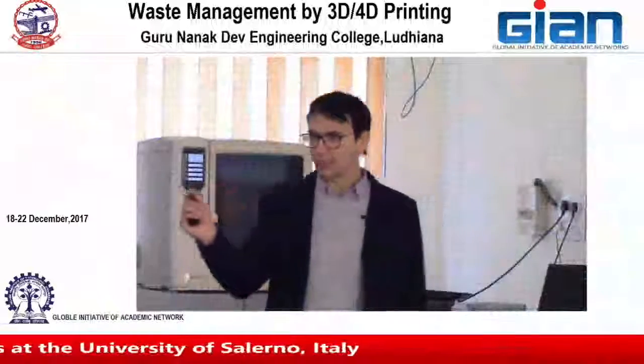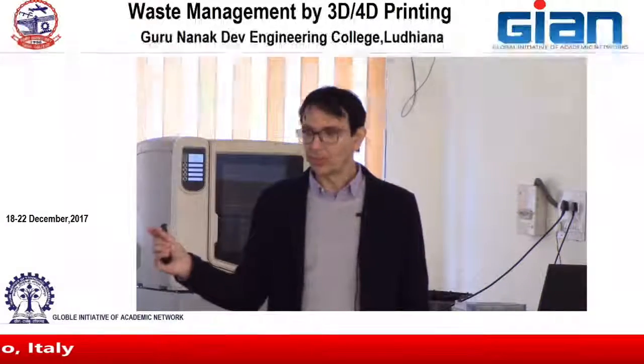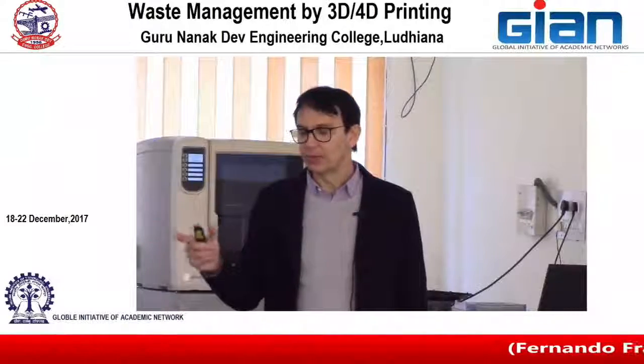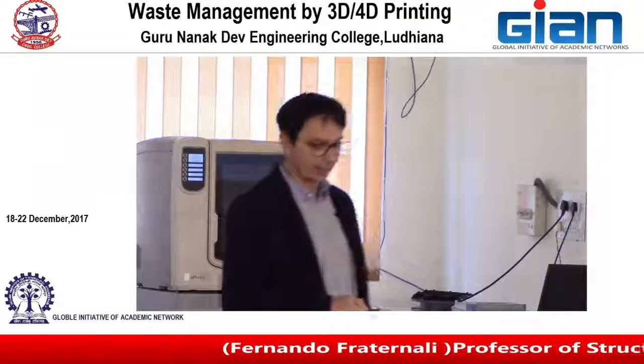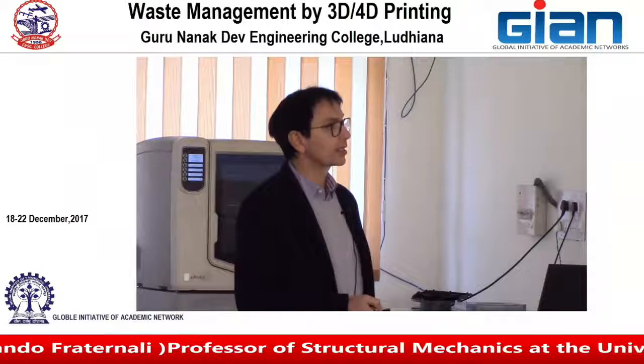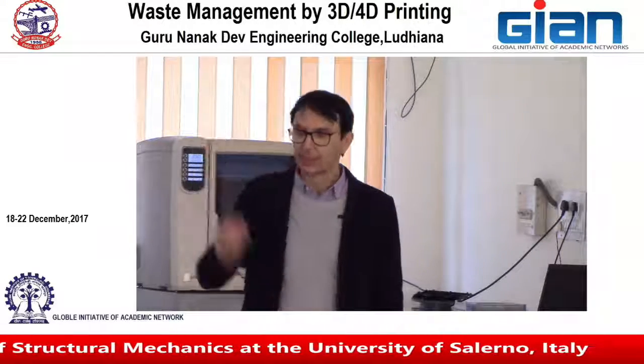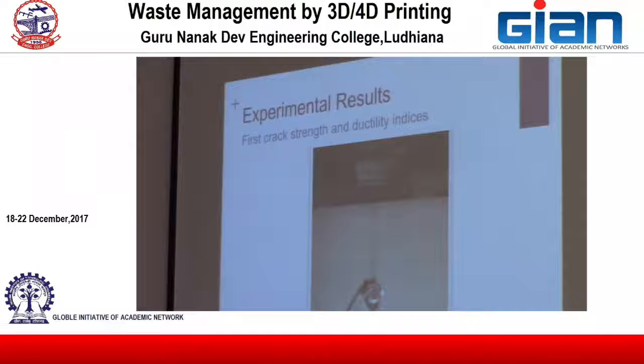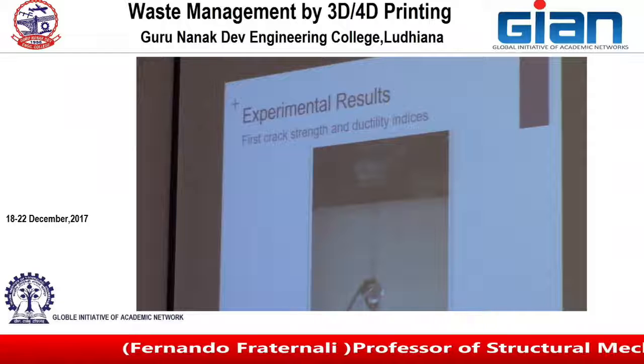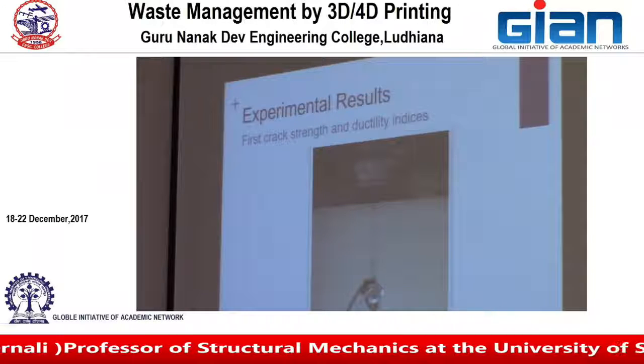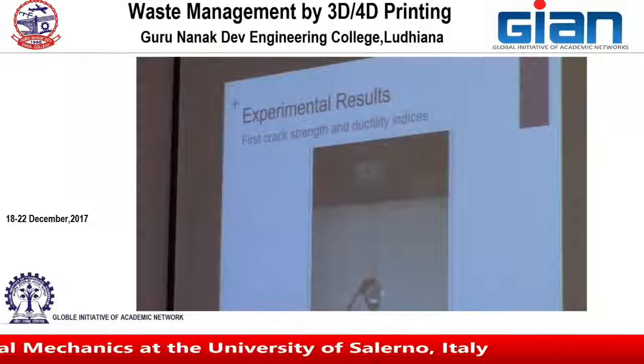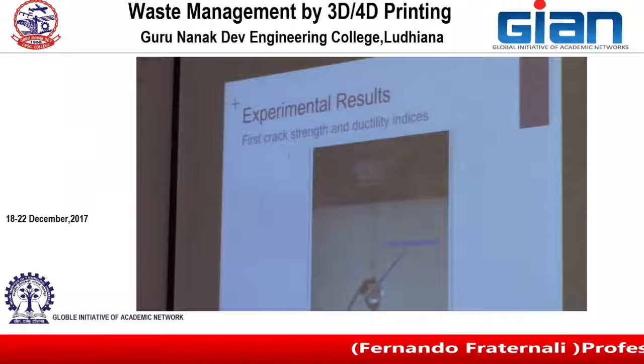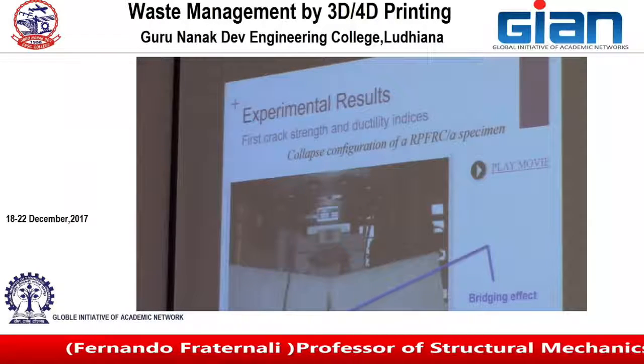You can measure the displacement of the tip or at the mouth, and you have two different displacements, but the most important one is the crack tip, so the displacement of the tip that needs to be applied to the specimen in order to perform the test according to international standards for bending tests on concrete specimens. This is a crack mouth opening displacement measurement, crack tip opening displacement measurement.